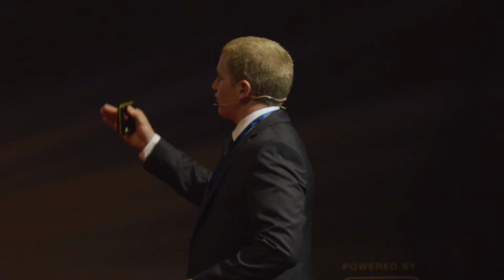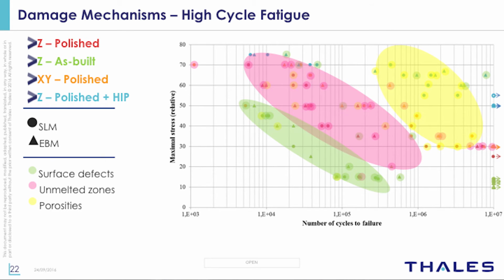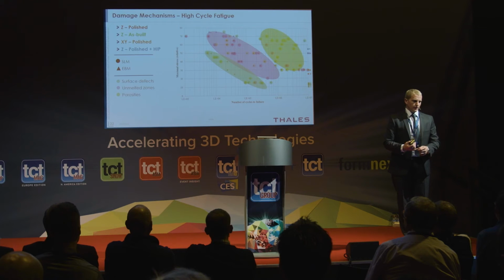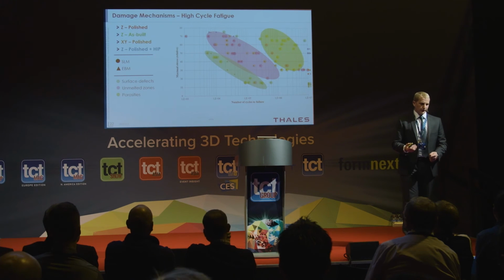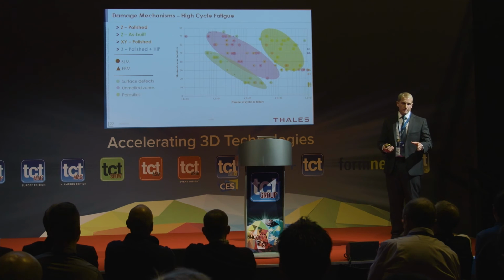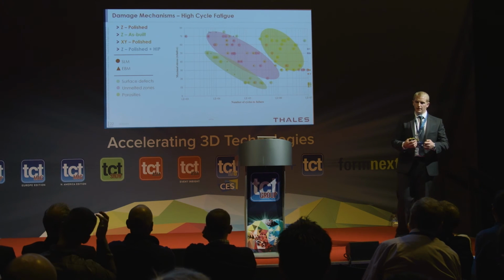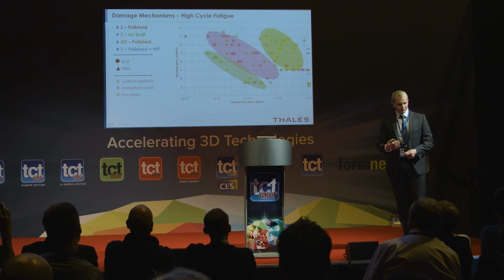So what I'm going to show you now is going on the defects that we looked at in a couple of slides ago. This gives us a few areas where the defects seem to be the main failure. So if you look at the green area down at the bottom left, most of these failures were due to surface defects on the test samples. Now these test samples were as-built samples, so there wasn't any post-machining or polishing on there.